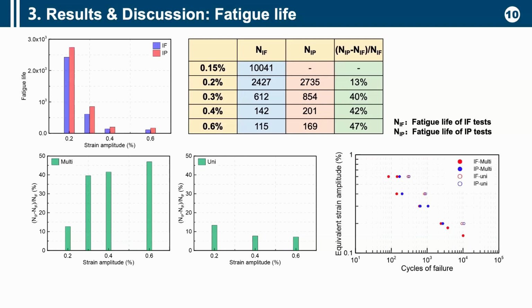With the strain range, the decrease percent is about 13% for this one, 0.2 strain percent, and for 0.3, 0.4, 0.6, it's about 40% decrease in the fatigue life. And if we compare with the uniaxial loading, the decrease is not so much.